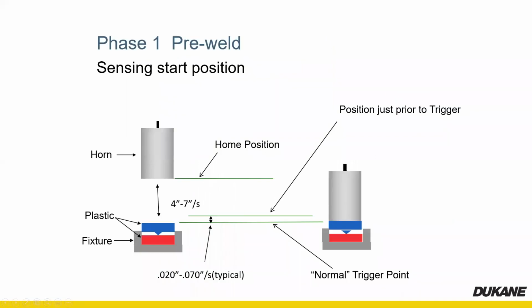With a pneumatic welder, that trigger point is determined by several things. You hit your palm switches or send a start signal, it turns the valve over, and the cylinder drives the horn down at some speed, a velocity based on the air pressure and the flow control setting. It then comes down and hits the part. If you've got a particularly high volume operation and need to go fast, you can hit your plastic with some pretty good initial forces, and those can actually create some problems.